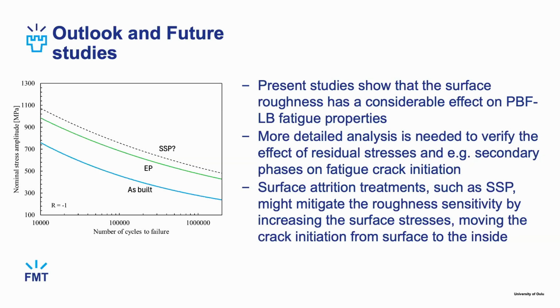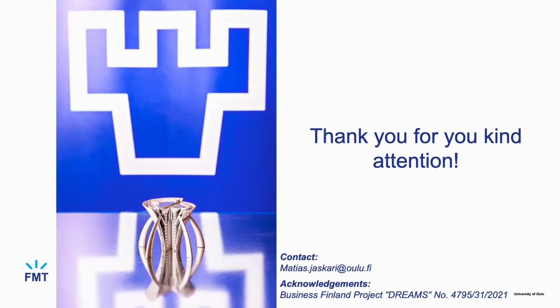But then we can also think further that instead of this electropolishing, which of course is a nice way to produce parts, but is also prone to deviation and so on, for example surface attrition treatments such as severe shot peening, how could they affect in these kind of hard but relatively ductile materials? This usually causes beneficial stress fields on the surface so that you move the actual crack initiation to the inside of the sample, and this usually is seen in a high increase in the fatigue resistance. But thank you.